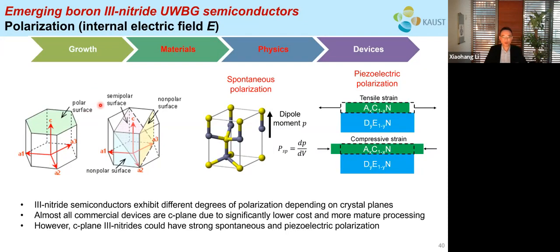Depending on the crystal plane and the material composition, there are different degrees of polarization. Basically, the so-called C plane, or the polar plane, has the strongest polarization, including the spontaneous and the piezoelectric polarization under strain. Also, most commercial devices are built on the C plane due to significantly lower cost and more mature processing, right? So the investigation of polarization for C-plane III-nitride is very important.